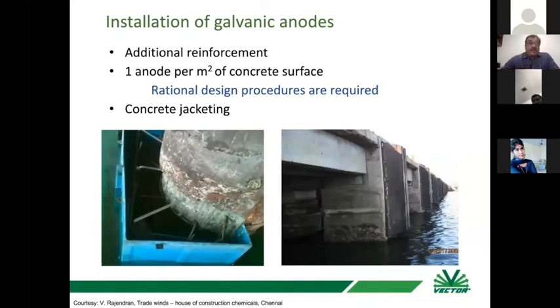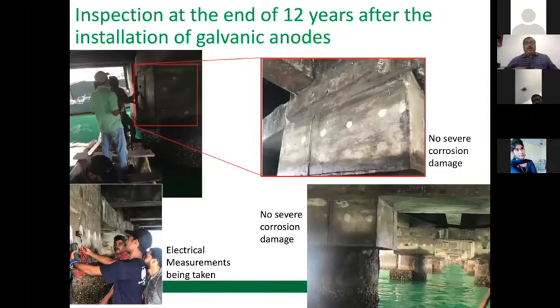Concrete jacketing was done in all new reinforcement. Anodes have been installed. What we did is after 12 years, even along with the IIT team, we had a visit there, and we found that there was no severe corrosion damage in the same structure where it was jacketed. Electrical measurements were taken, and it was found that the anodes are still protecting after 12 years, and within very, very high spacing, which we normally don't recommend now. But earlier we were having some limitation, but still it is functioning.